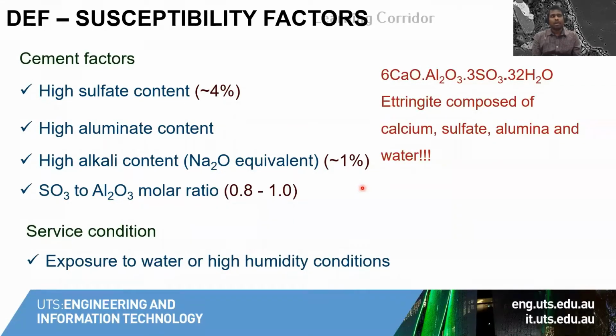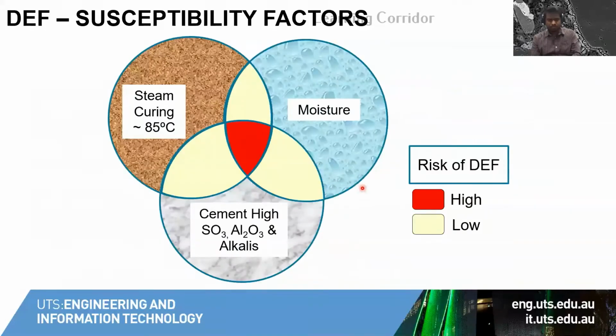Why? For DEF to occur in the system, the alkalis at least partially have to leach out from the system. Direct contact with water or high humid conditions will favor the leaching of alkalis from the system. So that is a very important factor.